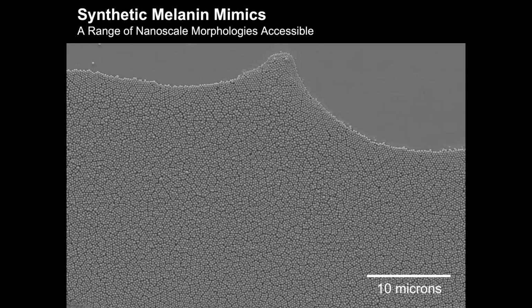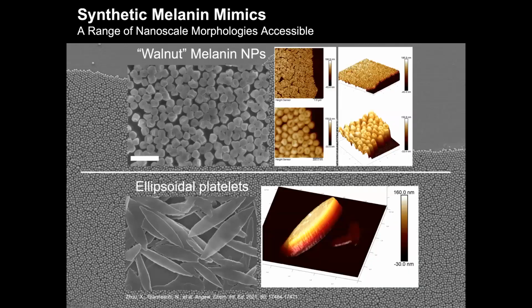What we see by scanning electron microscopy, and I'll show you a lot of images like this in transmission electron microscopy, if we do that kind of synthesis in water at elevated pH, is the spontaneous formation of spheres like this, so spherical nanoparticles. They look really beautiful, obviously, by SEM. And what you're looking at is 100, 200 nanometer objects that spontaneously form, right? So they're spontaneously forming spheres. We can control their size to some extent, their distribution, by controlling the rates of this reaction. So standard seed and growth pathways for nanomaterials.